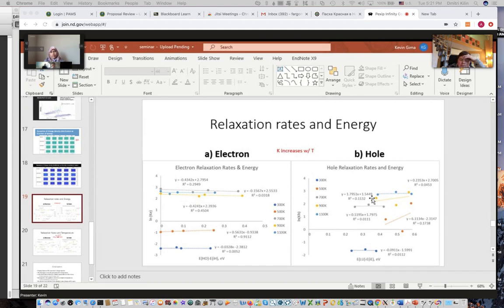All right. One final observation to point out is that essentially the higher the temperatures, the higher the relaxation rates. So from here you can see that my relaxation rates are directly proportional to the temperature. You can see that in panel A and in panel B. So just wanted to quickly point that out.